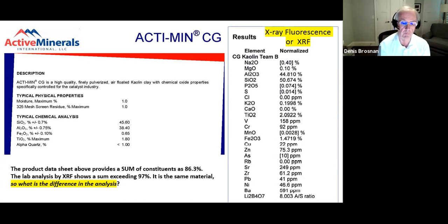Iron oxide is important because it's a flux in firing ceramics. In kaolins, it also tends to make them change in color as they are heated. It can color the final product. There's some TiO2, titania. That's a constituent of the ceramic chemically. It's about 1.8%. And most of the times when you have kaolin, you're going to have a little titania because it's naturally in the soils and the raw materials.